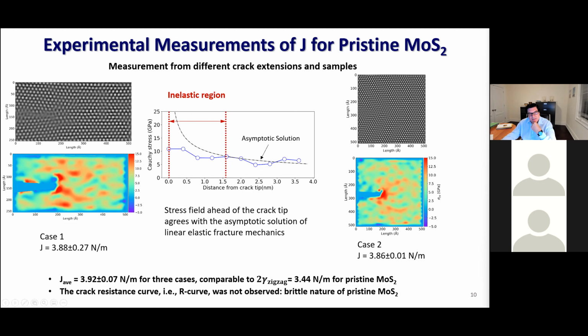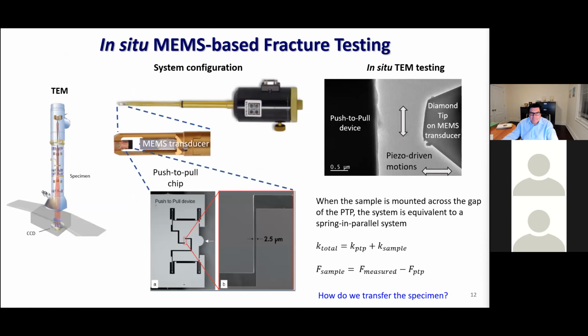The measurement that we did for molybdenum disulfide is represented here as an average over 3 cases. And if you compare with 2 times the surface energy, which would be a Griffith type of criterion, you have that it is on the same order. So brittle fracture is what we would expect also given the failure of these materials. And there is no R curve in this case.